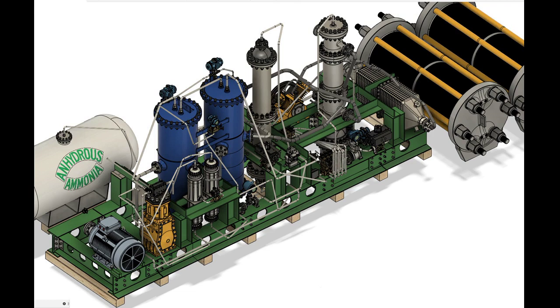For large-scale plants, the volume may be less important than the conversion rate per loop, hence the choice to operate at lower space velocities. For small-scale plants, however, what is desired is maximal footprint reduction, hence the choice to increase space velocity at the expense of conversion and pressure drop. The higher converter material loading is tolerated as a necessary design compromise that is unavoidable by downscaling. The additional material loading from downscaling pales in comparison to the total system capex, principally dominated by the prime mover, namely the electrolyzer, solar farm, or wind farm.